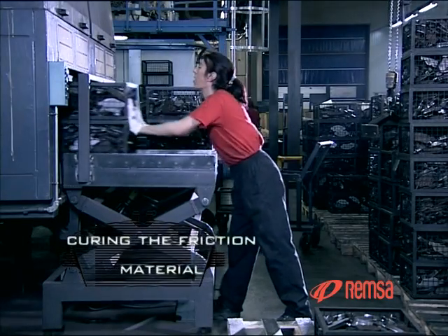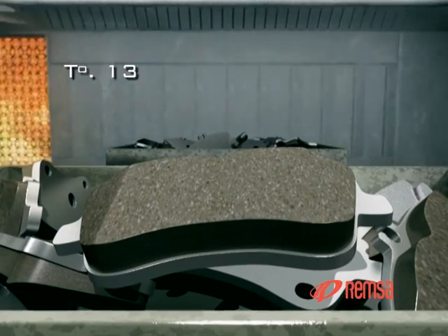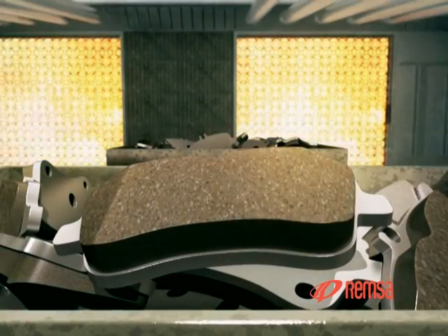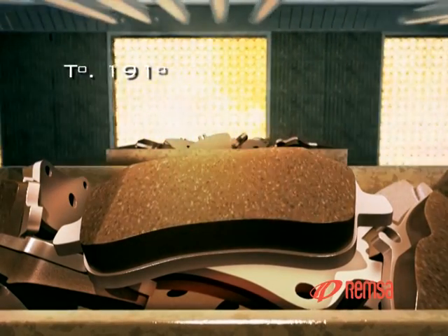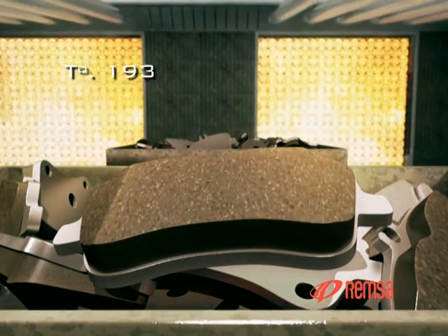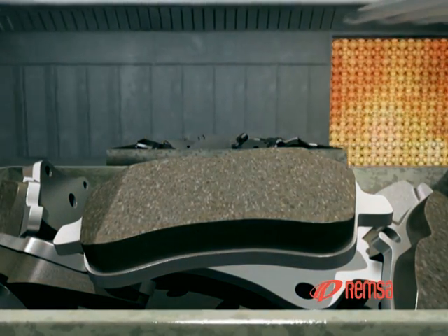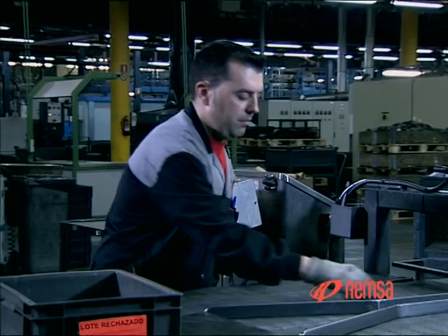After pressing and sticking the material to the backplate, the pad moves on to a curing process which takes place in continuous ovens, where for between 7 and 10 hours it is subjected to different temperatures, from the ambient temperature to more than 200 degrees centigrade. The production batches are inspected thoroughly to check there are no cracks or flaws in the surface of the pad.